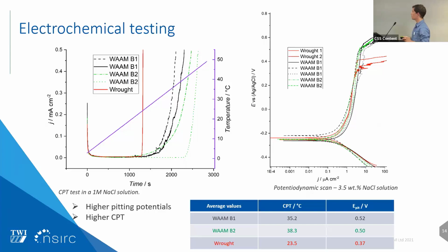Here we can see we have a classic active to passive transition, which is expected from a stainless steel. All the WAAM samples had higher pitting potentials. We can see here on the table below that we are around 0.5 volt for the pitting potential, and for the wrought samples we are below that, sitting at 0.37 on average, counting those two here.